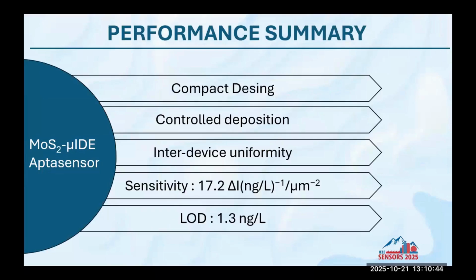Now, with this, we have designed a compact electrochemical setup, which can be used for in situ application for heavy metal ion detection. We could control the deposition, and we have got very good inter-device uniformity, and the sensitivity and LOD of the sensor are as shown here, which is well below the safe limit reported.